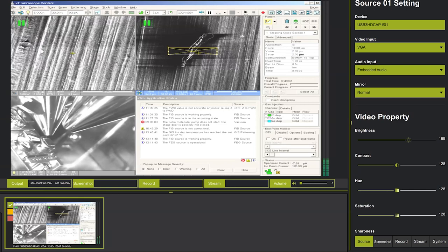If I ask the instrument to remove 10 micrometer by 2 micrometer by 2 micrometer with the current condition, it says it's going to take 48 minutes. That's too long. So what I'm going to do is increase the ion beam current to 2.8 nanoamp. That's about right. The actual measurement is 3 nanoamp there. And it's going to take a minute and a half, less than 2 minutes. So let's check it first.